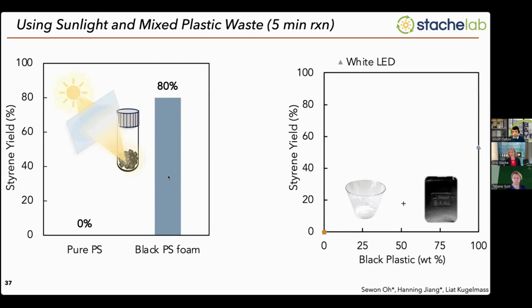But the really exciting thing was that all of this is based on black plastic, right? If we have clear white plastic, nothing happens. We questioned, because we're not consuming the carbon black, could we use the black plastic to first depolymerize that polystyrene and then essentially use it, I won't say as a catalyst, but use that carbon black to depolymerize white polystyrene in the same mixture. And so what Hanning did is she took different weight percents of black plastic with clear plastic, from 0 to 100 weight percent, irradiated the mixture with white LEDs, and in all cases, she found depolymerization of both pieces of plastic. So it first depolymerizes the black plastic, and then that carbon black can be used to depolymerize the clear plastic.